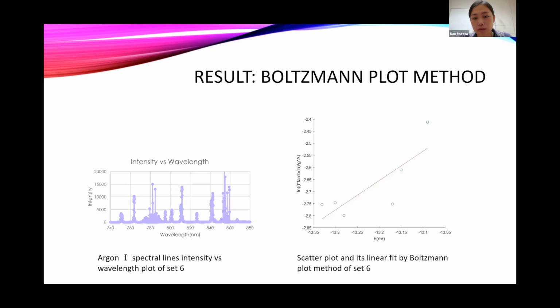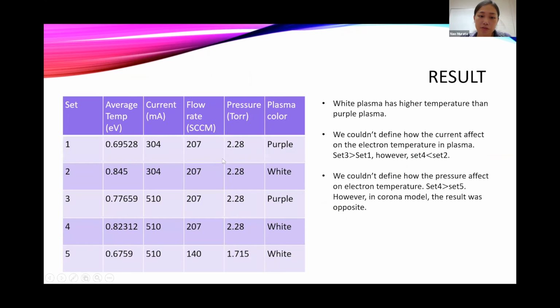And next result is from Boltzmann plot method. Left plot is from the OES data, which is argon-1 spectral line intensity versus wavelength. And right side of the scatter plot and linear fit is from the Boltzmann plot method of set 6. So we use this slope to get the temperature of the electron. So this is a result.